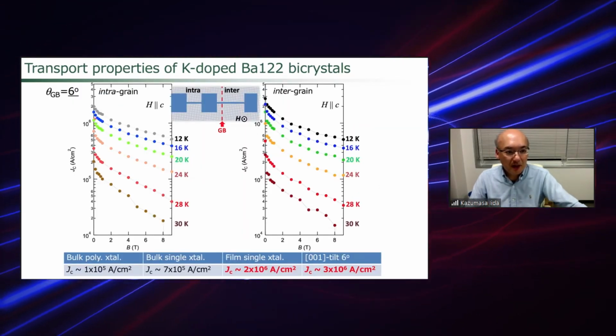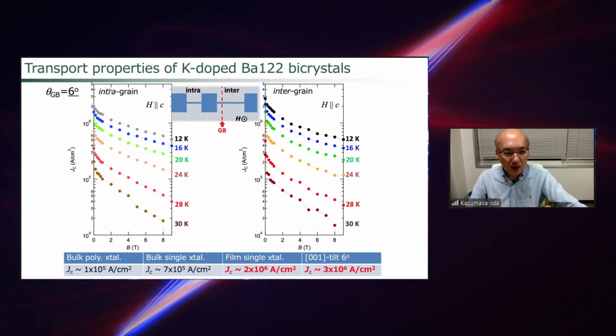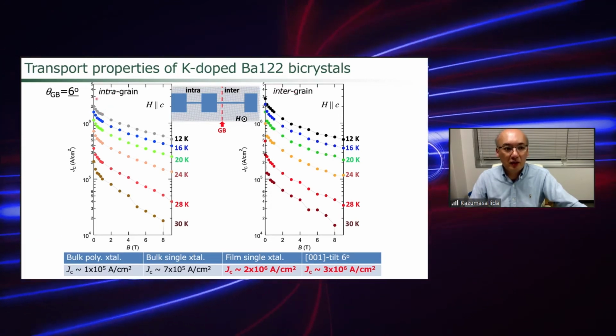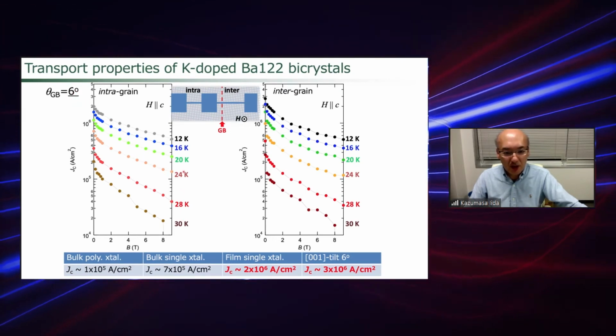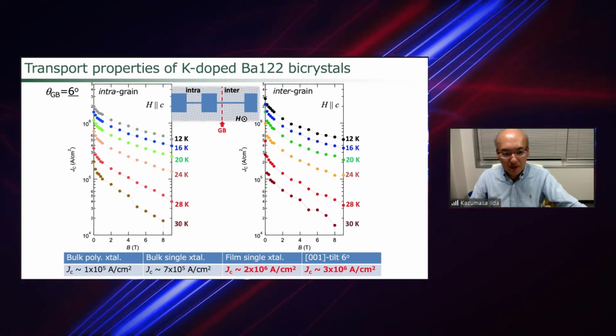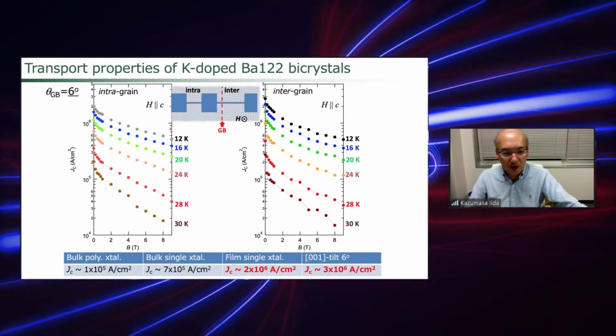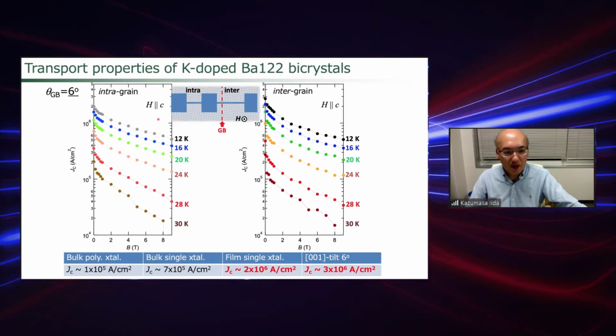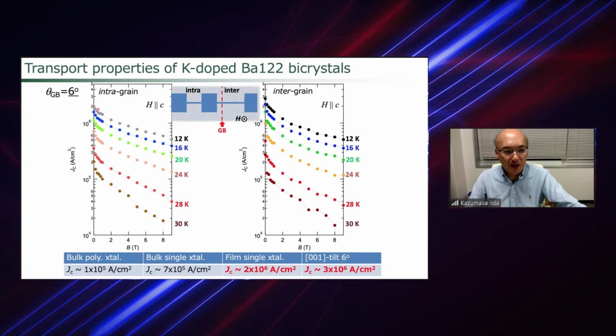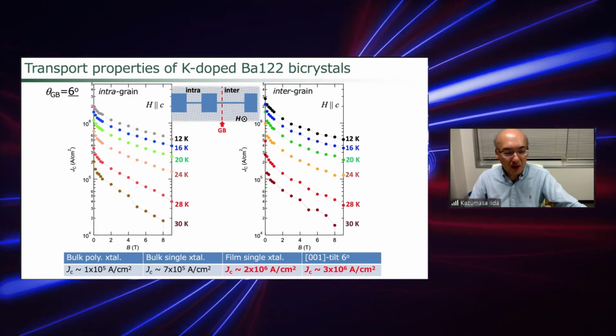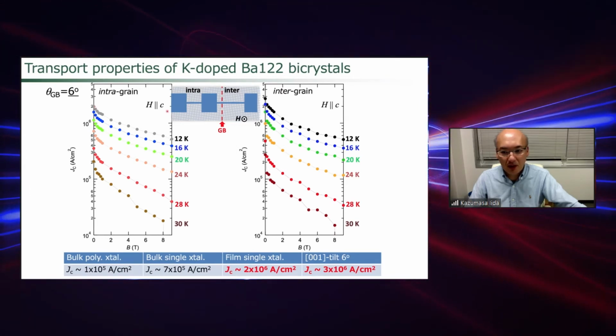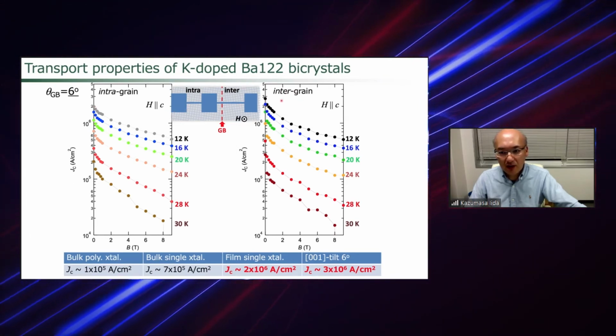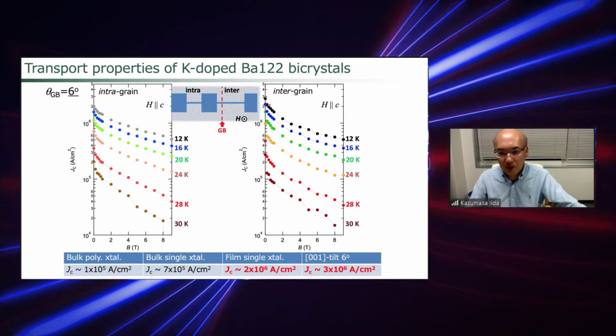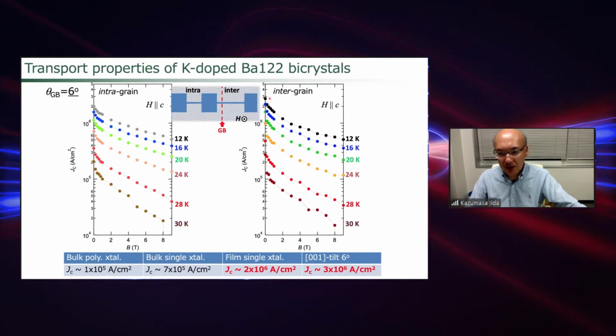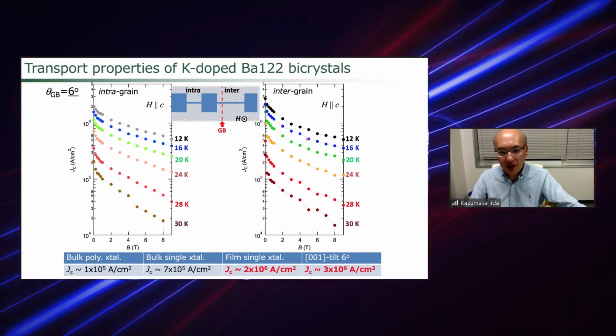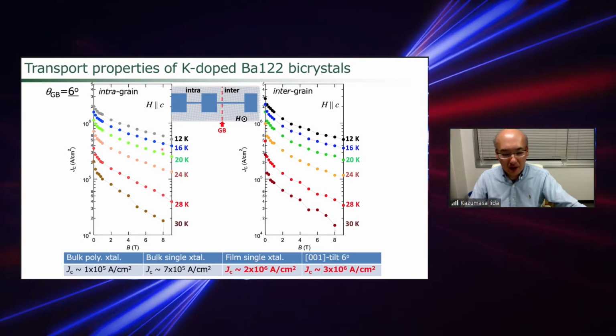Okay, here is the field dependence of the critical current density of the intragrain and the intergrain bridges with the grain boundary angle of 6 degrees. We measured from 12 Kelvin to 30 Kelvin, and below 12 Kelvin, unfortunately, we cannot measure because of heating problems. And you see that the self-field Jc of the intragrain is almost at the level of mega ampere per square centimeter at 12 Kelvin, which is almost the same as the intergrain Jc. And for the intergrain bridge, we applied a magnetic field, but the Jc does not decrease significantly, which is almost the same as the intragrain behavior.